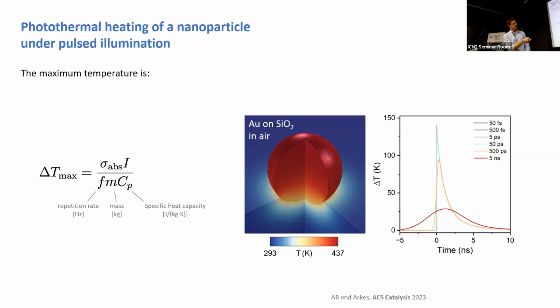And then we vary the pulse length from 50 femtoseconds to 5 nanoseconds. And what you see is that the maximum temperature that this particle experiences when the pulse arrives really doesn't depend at all on the pulse length, unless you have very, very slow pulses.